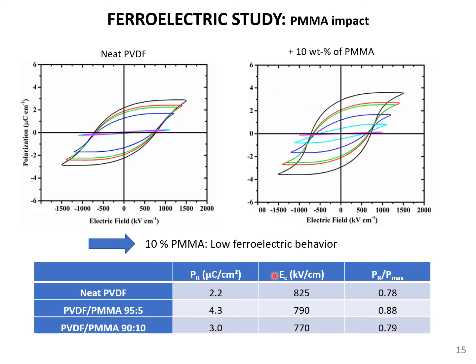However, when you add 10% of PMMA, you don't modify the coercitive electric field, but you have a decrease of the remnant polarization. In other terms, you don't accumulate so much charge by comparison with the blend containing 5%.